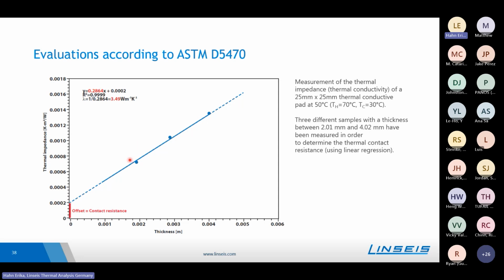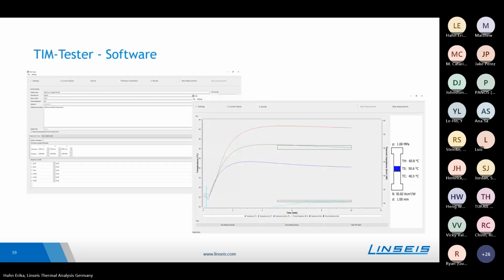For solids, the easiest would be to just prepare 3 different samples with different thickness. It's also possible to stack several samples on top of each other when there's only one sample thickness available. In case of pastes, for example, one just applies the paste onto the meter bar and compresses it step by step using some pressure with the actuator. Here you can see a screenshot of the software.